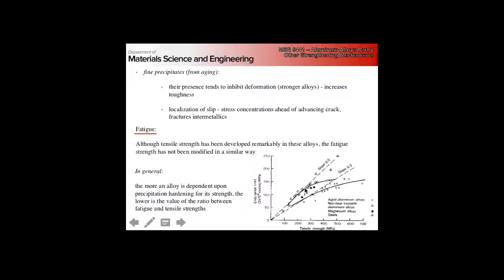But notice these lines. So this is, which one's which? Okay. The non-heat treatable are these open circles, and the aged are the X's. But notice that this line curves, meaning that we have a hard time increasing both strength and fatigue life. So the higher our strength goes up, the smaller the ratio between fatigue life and strength becomes. And now compare that to steels. This has a much higher slope for certain types of steel alloys. So in those cases, we can retain both the fatigue life and the tensile strength.